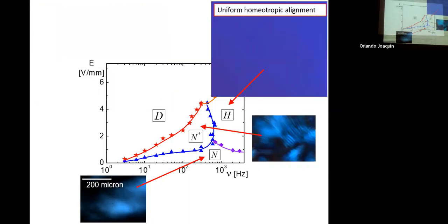And then at high frequency you have this uniform state where the rods are aligned along the field. You can show that for frequencies higher than about this frequency, there is no charge polarization anymore - the frequency is too high because the ions cannot follow the field anymore.